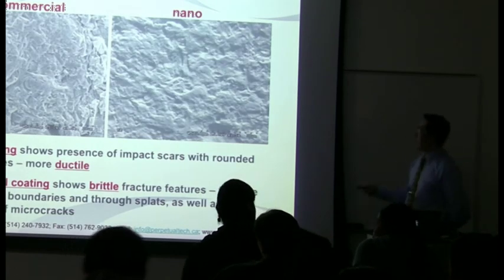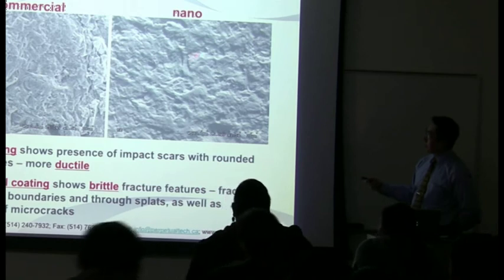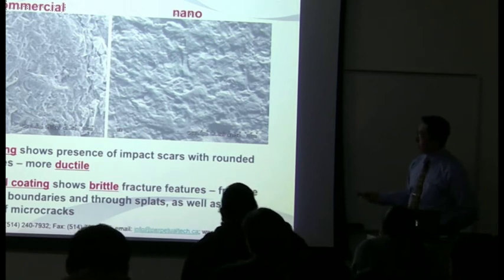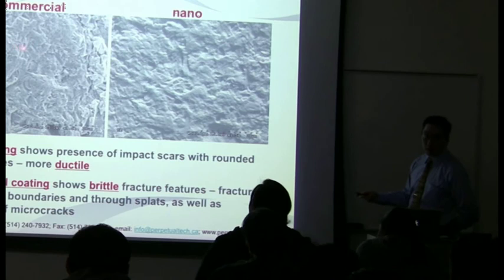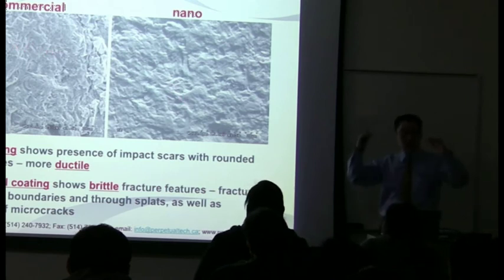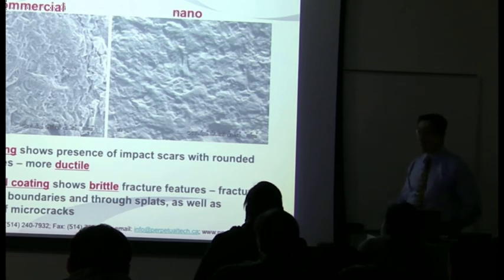And even at high angle impingement, you have higher roughness, but compared to the commercial coating, you see that it is smoother. The craters, the edges of the craters are rounded. And that's, once again, what you typically see with metals and polymers.